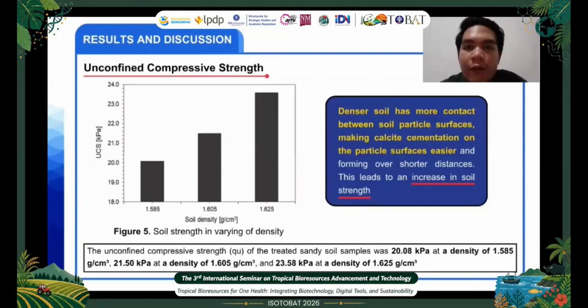The high UCS value was obtained for the sample with the high density. It is because denser sand has more contact points between particle surfaces, facilitating the calcite cementation process over shorter distances and thereby enhancing the strength of the soil. Consequently, the mechanical strength of the soil depends not only on the amount of calcite formed, but also on the arrangement and contact between soil particles.